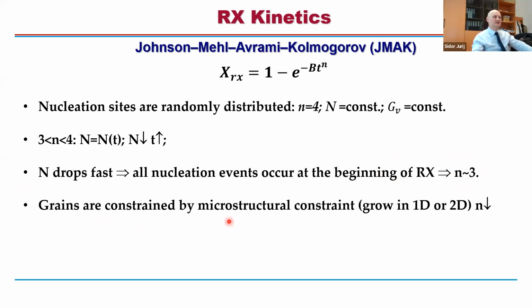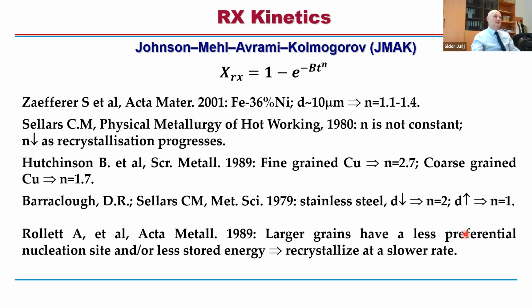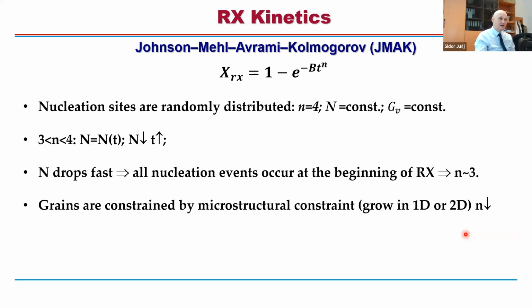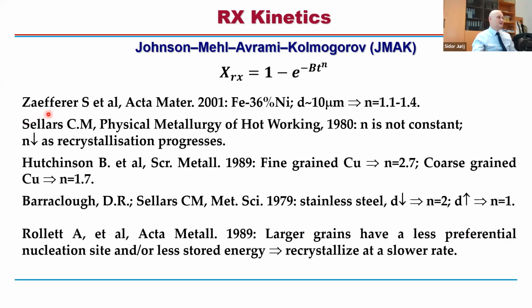Then grains are constrained by microstructural constraints. So when the grain can grow in only one direction or 2 directions, for instance, you have columnar grains, or when it grows only in 2 directions, right? And also it will deviate from this ideal case, it won't be 4. So the question is which one to choose. Then various groups, those are, I would say, earlier investigations in the 60s, 70s. Then a later investigation by a group like Stefan Zaefferer and co-authors, they published a paper in 2001 in Acta Materialia where they investigated an iron-nickel alloy with a grain size of 10 micrometers. And then it turned out that N is very close to 1, or was varying between 1 and 1.5.